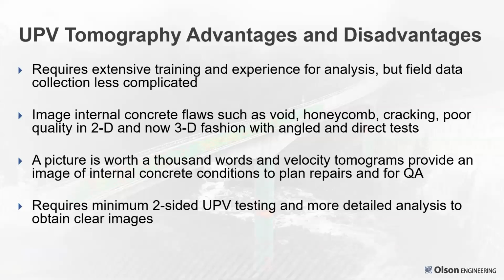So the tomography has some advantages and disadvantages. It does take some training experience for analysis. The field data collection is straightforward, but it takes time because you're doing many more tests. It does allow you to image flaws such as void, honeycomb, cracking, poor quality concrete in a 2D and even 3D fashion if you do more tests between each of the cross sections. But normally we were testing every 2 feet along this beam and not trying to do angle tests between them.